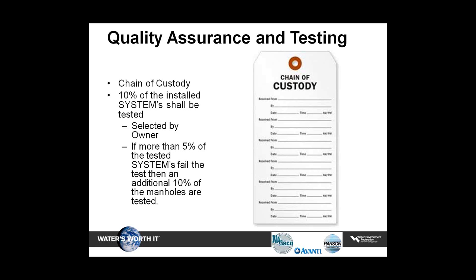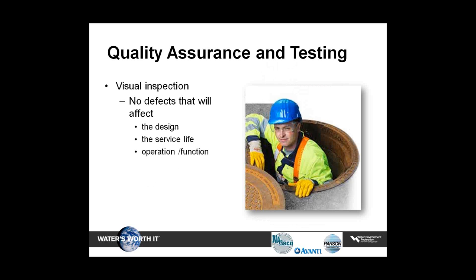Some of the quality assurance and testing measures require the contractor and owner to keep a chain of custody. The contractor shall perform all testing in the presence of the owner's representative. 10% of the installed systems shall be tested. If more than 5% of the tested systems fail the test, then an additional 10% of the manholes are selected for further testing. This process continues until the systems tested meet the requirements.